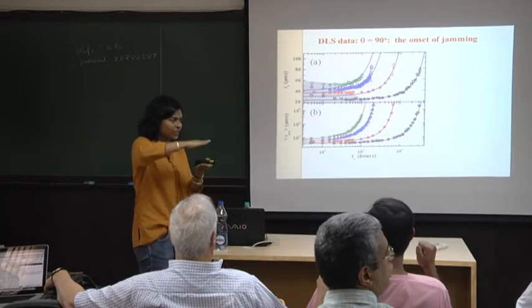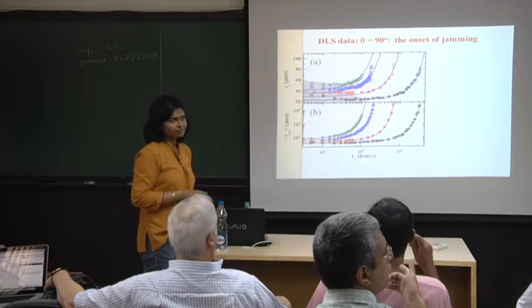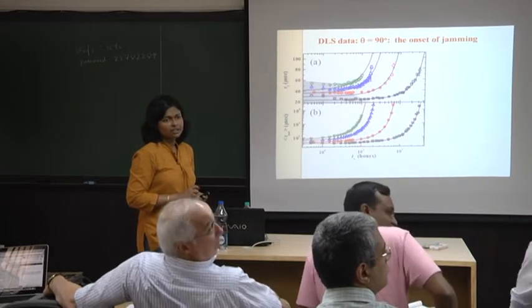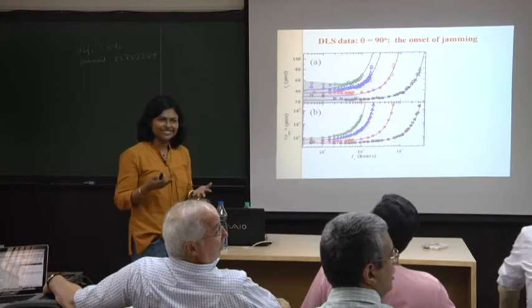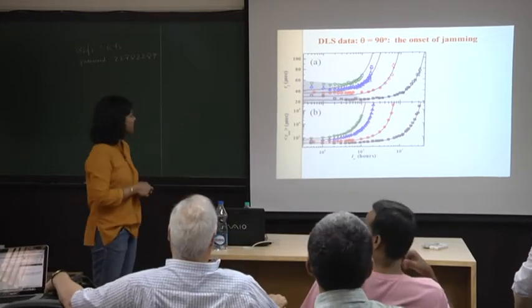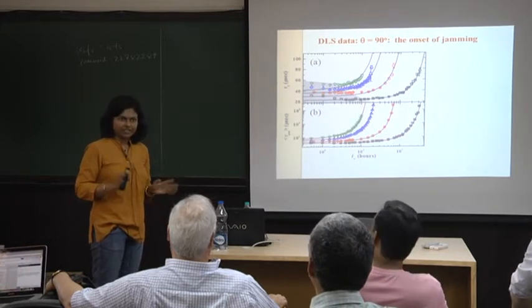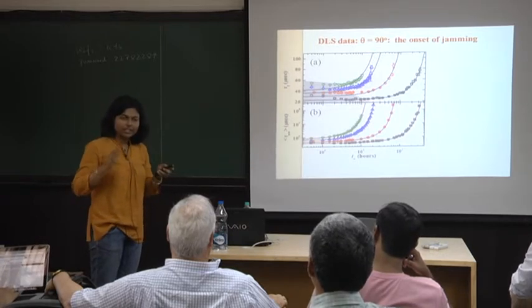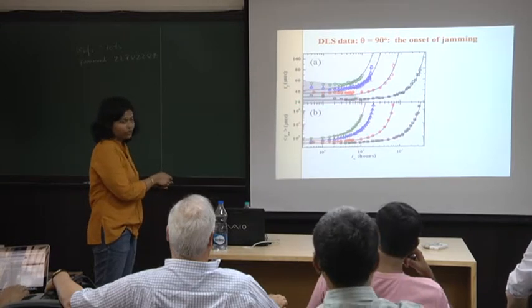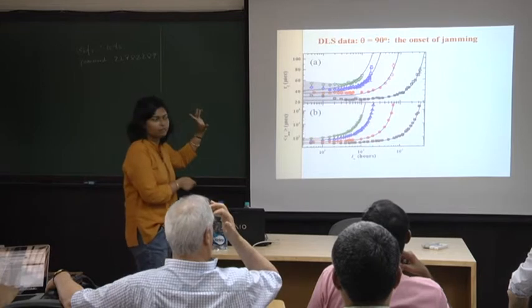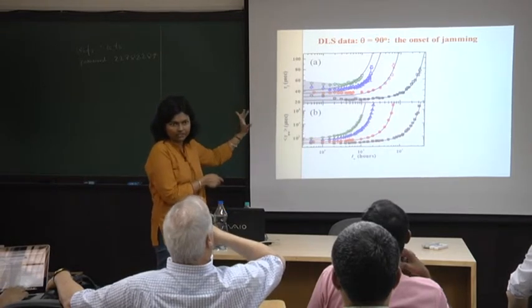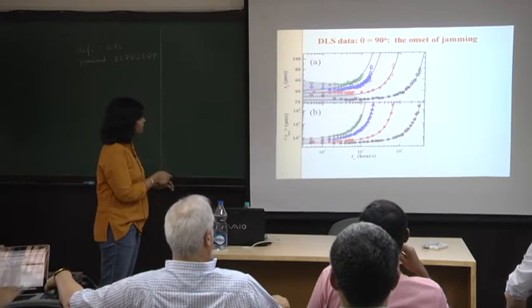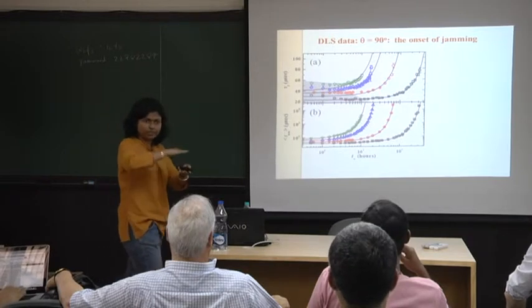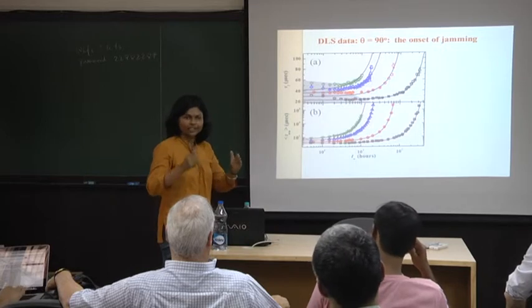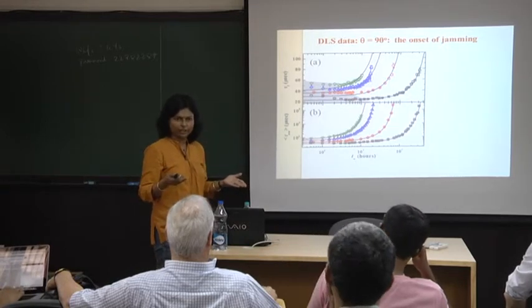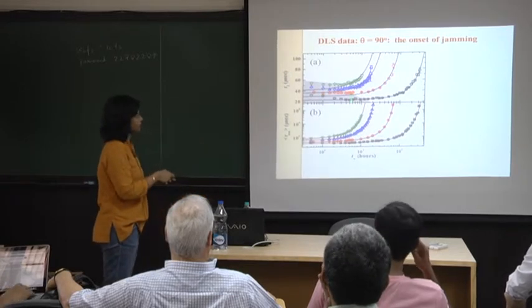So his point is that first I had stacks that broke up. Yes, correct. Now, to answer your question, that breaking up happens very fast. The breaking up of these stacks into individual particles, this is where that happens. So here you can see this is the fast relaxation time. This is where you are really measuring the fast relaxation process of the particles. You can see that the fast relaxation process is becoming smaller, and that is because your tactoids are breaking up into smaller entities. After that, the sodium ions are now out in the solution, the clouds are repelling, and that's what takes over here.